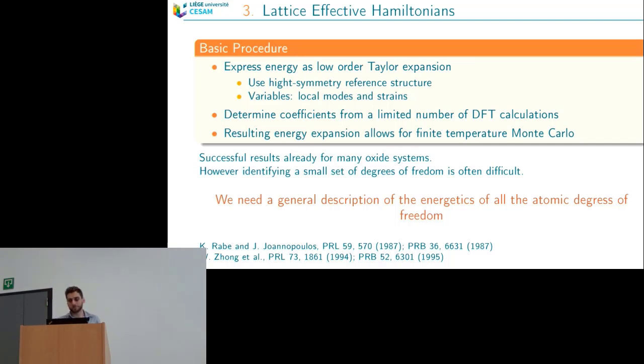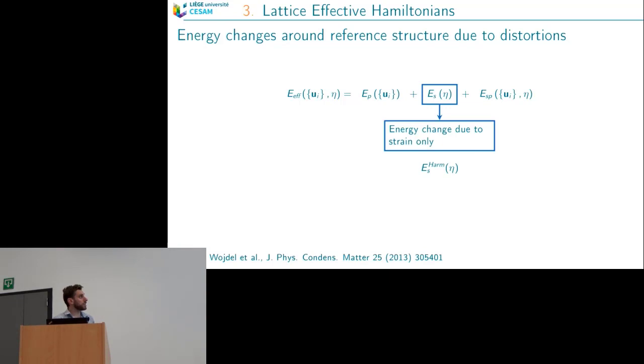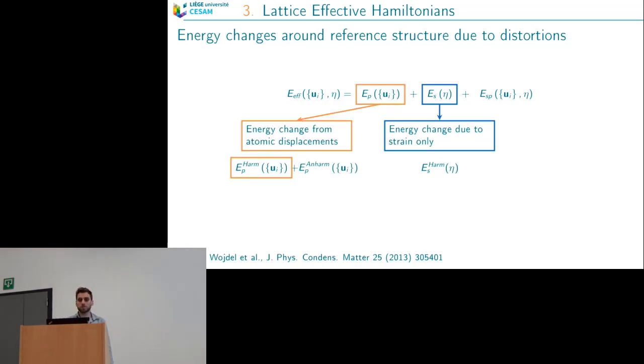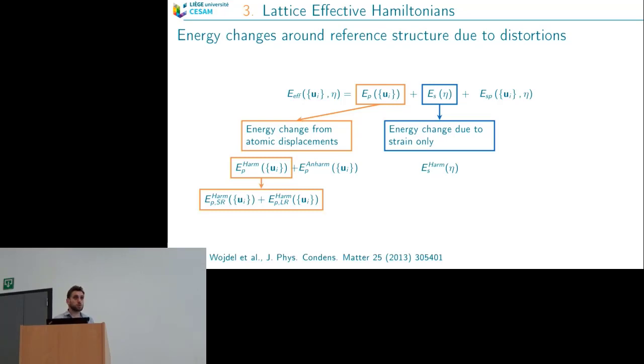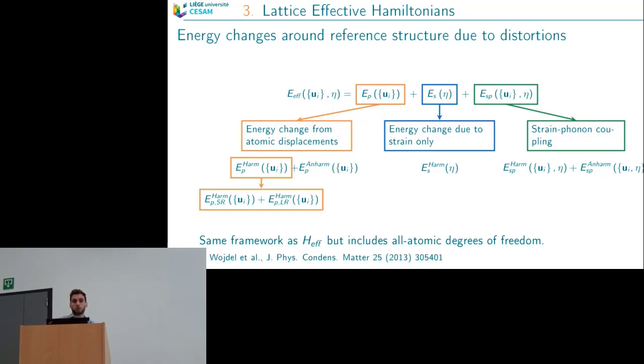Here we want a more general description of the energy surface that includes all atomic degrees of freedom. The lattice energy can be expressed in three parts: the strain energy (harmonic only), the phonon energy from atomic displacements (split into harmonic and anharmonic parts, with the harmonic further split into short-range and long-range for oxides), and the strain-phonon coupling (with both harmonic and anharmonic terms).